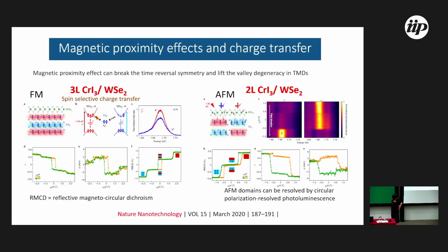For example, this material is not stable in air, so you have to encapsulate it because there is degradation. And there's a hot discussion about magnetic proximity effect. People say only the interface is important. But here they show that you can have magnetic proximity effect for the second layer as well. Because this material, for example for 3 layers, is ferromagnetic, for 2 layers is antiferromagnetic. And they can show that they can see other layers. It's not only the interface. The interface is ferromagnetic. They showed this work 5 years ago. And there is this discussion. But nobody has studied these heterostructures with antiferromagnetic materials. And when I decided to do this, people said, you are crazy. But I was interested to investigate.